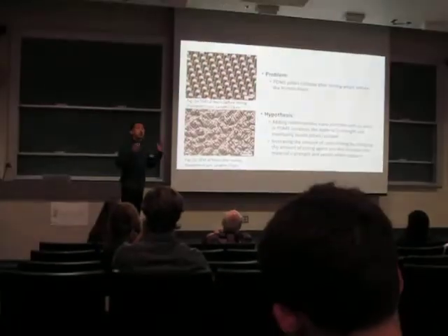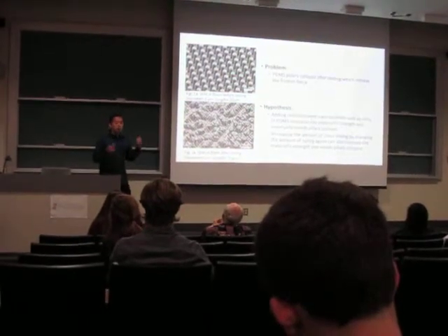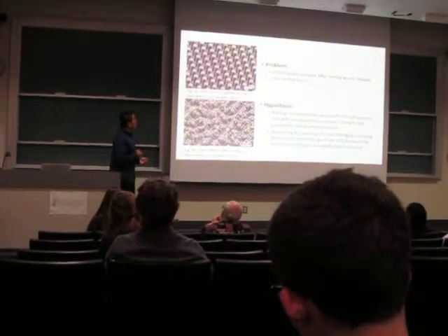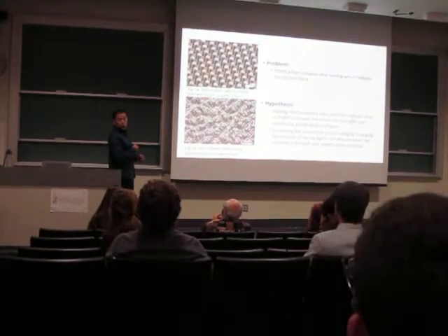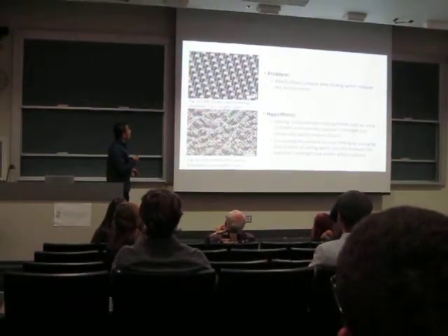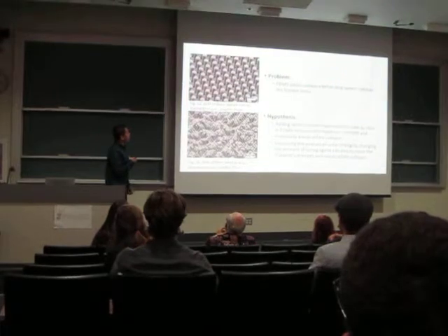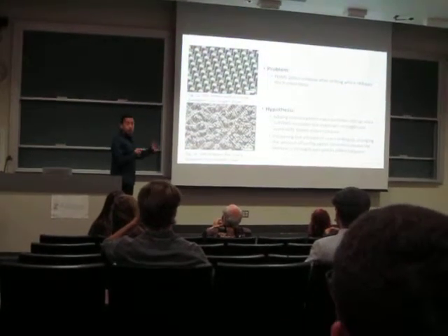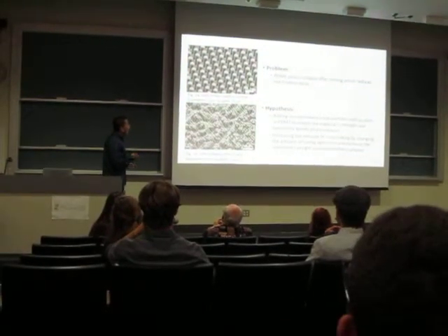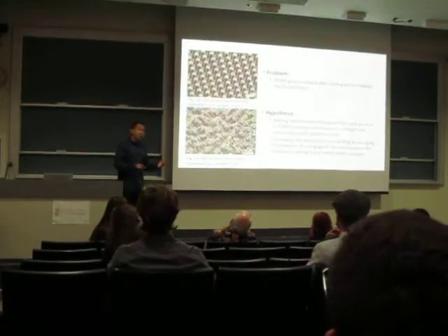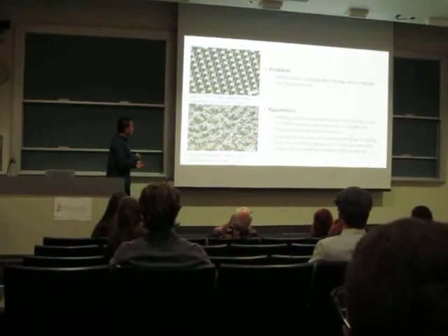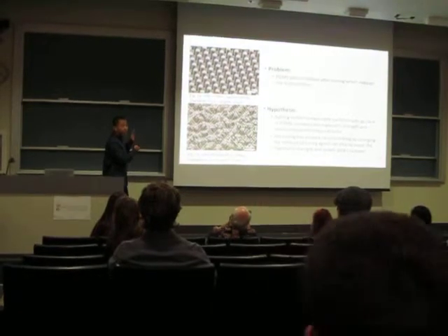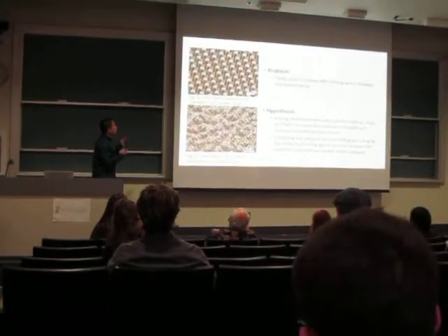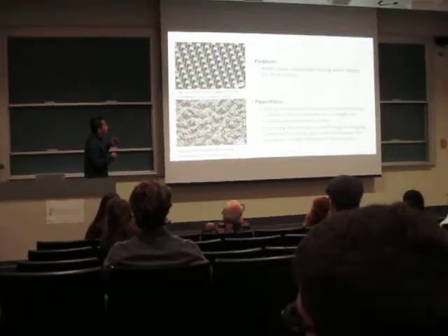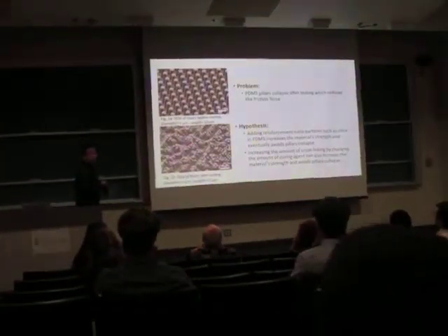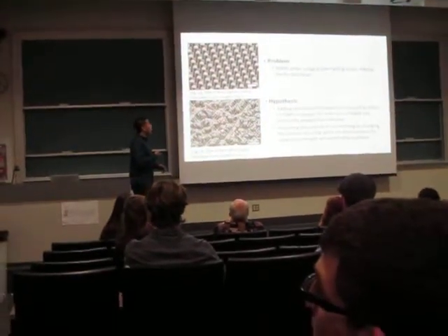But after talking about all these good things, we have a problem here. That's why I need to do research on it. This is the sample we made, and that's the SEM picture. The diameter is about 5 micrometers, and the length is about 25 micrometers. After we tested on a glass substrate, we had a problem. As you can see, this is the ideal situation. And now, after testing on the glass substrate, those pillars collapse. So this is a problem.